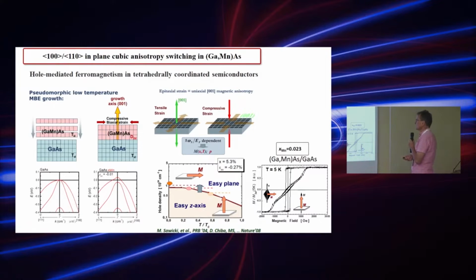I mean, there are some other cases, but the main source of these materials are epilayers grown by MBE techniques. These are grown on gallium arsenide, and depending on the difference between lattice parameters, we can usually obtain materials in compressive strain, but if we use some stressor layer here, we can obtain the tensile strain case. And the major physics I'm going to talk about actually takes place at the top of the valence band, and this is the splitting of the valence bands into heavy holes and light holes, which is responsible for the magnetic properties and magnetic anisotropy most predominantly.